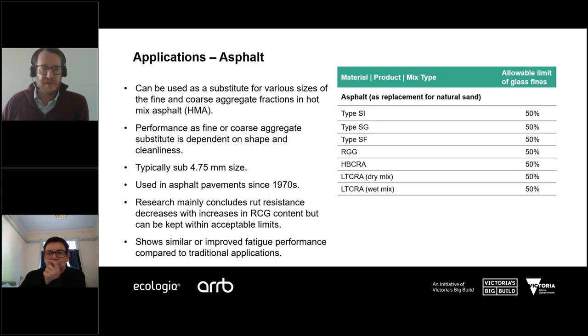So now I'm just going to move on to asphalt. And again, there's options to substitute for various sizes of fine and coarse aggregate within hot mix asphalt. As I alluded to before, typically we would be considering a sub 4.75mm size product, and this product is crushed to give it a continuous grading, and therefore is used as the fine aggregate replacement.